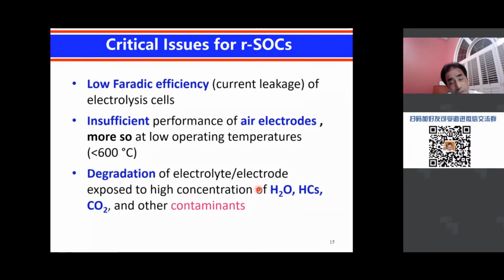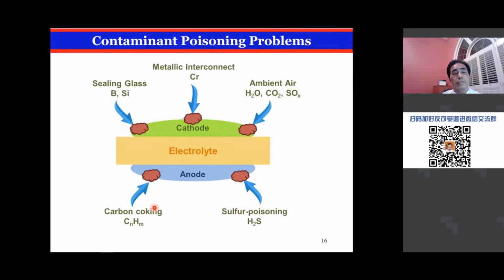Now, for the reversible operation, especially for electrolysis of water, the water content can be very high. A lot of the conventional materials will have stability issues when they're exposed to high concentrations of water, to hydrocarbon fuels, and to carbon dioxide. And more importantly, some of the contaminants. When we have a fuel cell stack, inevitably there are impurities from sealant, and there's chromium from interconnect materials, and contaminants from ambient air, and also sulfur-containing species if you are involved in any hydrocarbon fuel, and the coking. So for the anode here, especially if we're talking about using natural gas to power a fuel cell, the contamination from the contaminants within the natural gas could be one of the major challenges.